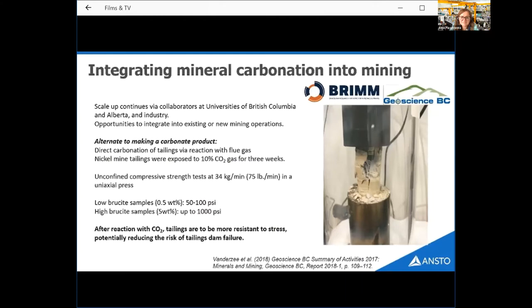And this is the work of a student there recently who reacted nickel tailings with 10% CO2 flue gas for 3 weeks. And what they found is that there are additional benefits to doing this in stability. So this experiment shows that the more carbonated the tailings become, and here we're looking at two levels of brucite. Brucite's the most reactive mineral, so it's a proxy for carbonation. But the more you carbonate the tailings, the more compressive strength tailings gain.